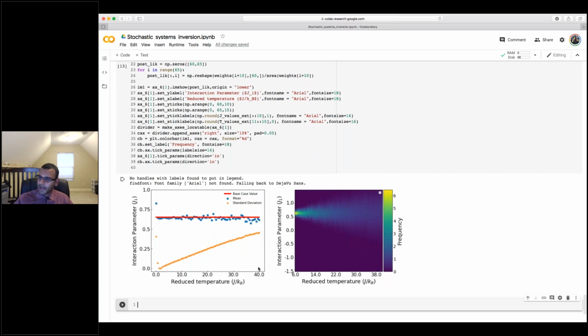So a few things. First thing is, even at a ridiculously high temperature, right, of 40, where you would assume that all you see is kind of random configurations, apparently there is still enough information in those images that your reconstructed interaction parameter is really close to the actual value, right? The standard deviation increases with temperature, as you would expect, but even when you sample very, very far from the phase transition, apparently there is enough information present. There is enough non-randomness, as it were, present to be able to derive an interaction parameter that actually makes some sense.